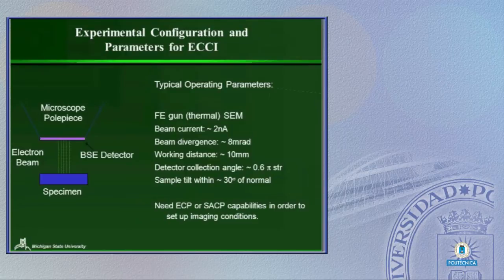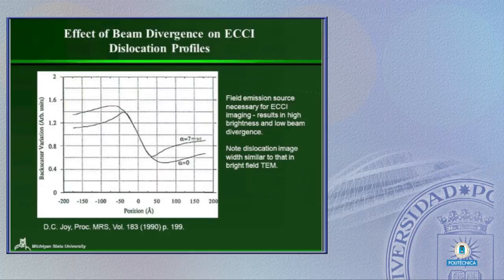This typical backscatter detector with these working distances gives us a fairly large detector collection angle, which is very useful for us because what it does is gives us a lot more electrons on the detector, which really makes life easy. And one of the critical things for us is generally you're going to need to be able to collect these channeling patterns in order to set up the proper imaging conditions.